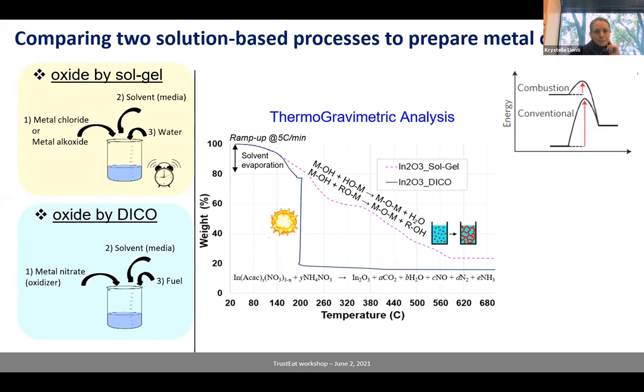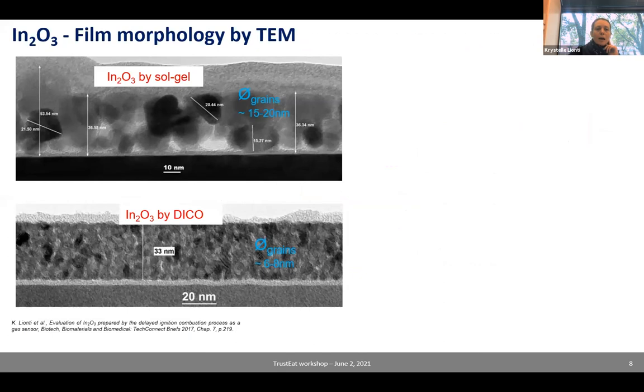So here I'm showing a couple of examples of things that we have achieved. On these two images are indium oxide thin films prepared by either Sol-Gel or DICO. In both cases, we have about the same thickness, 35 nanometers or so. So as you can see, much thinner than the commercial sensors. And the main difference between these two films is the grain size. They're both on the low side,